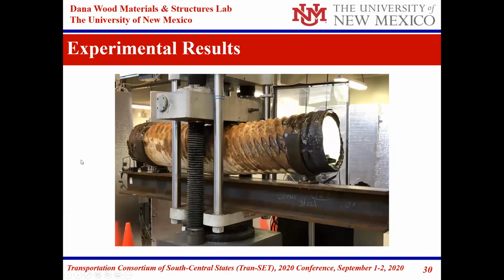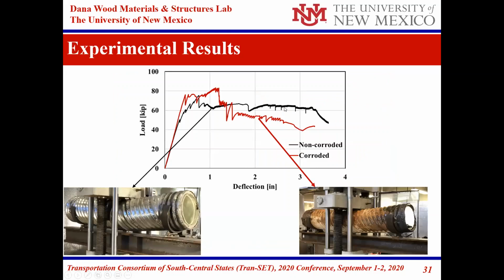Again, you can see a very ductile system with adding the GFRP to the corroded pipe. By the way, if you see some of the field pictures of this, you will see right away that there is very large deformation, up to where the road, as we've seen, could fail. Comparison between the two, that is the load deformation or deflection of the non-corroded pipe and the corroded pipe. Very similar behaviors. So the GFRP basically can take the load and can completely be integrated with the system, whether the pipe is corroded or non-corroded.